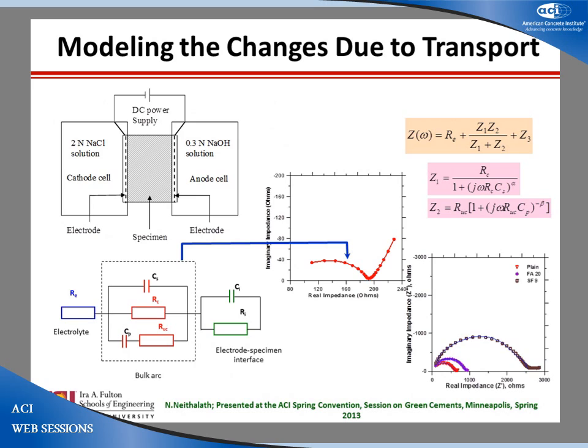So here is some models to actually bring home the point of what is happening. And this is a very simplified version of the model. So here is your electrical impedance spectra that gives you the real impedance versus imaginary impedance. So this was done from 1 Hertz to 10 megahertz frequency range. And here is how we are doing the model for the concrete. So basically you have the electrolyte here. Chloride ions go from catholyte to the cell and goes inside. During the non-steady state migration duration, you are not going to get chlorides here because breakthrough point has not yet achieved. So your chlorides are only in the specimen, not going completely.